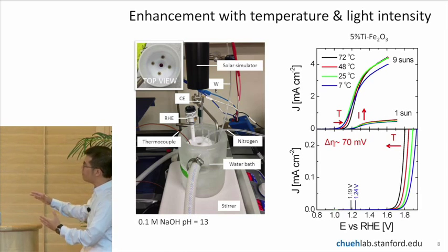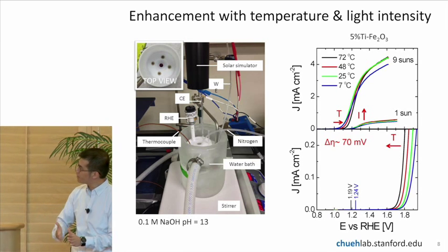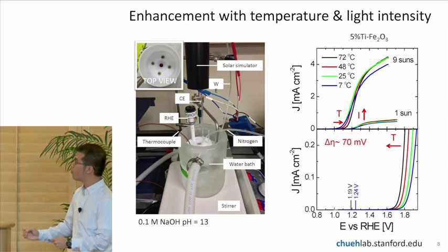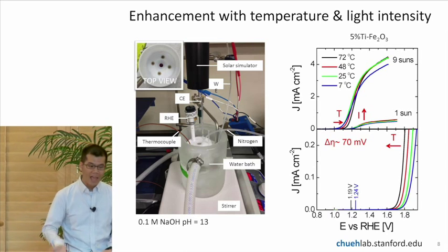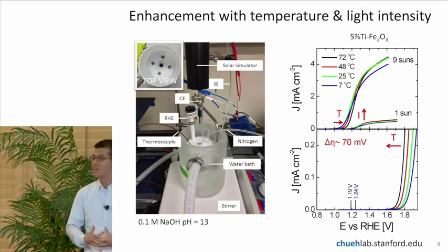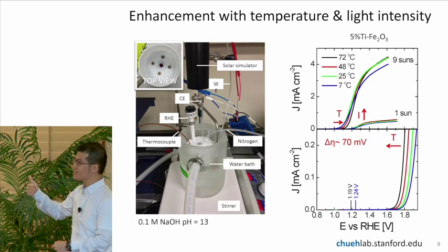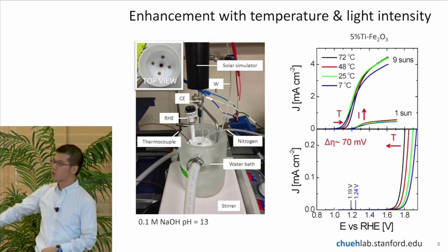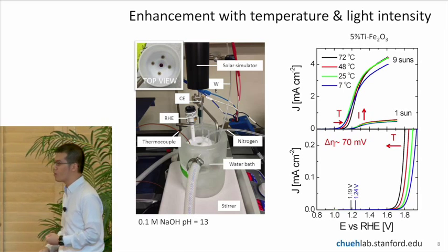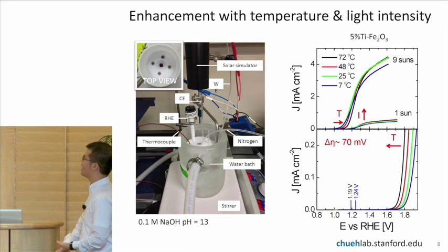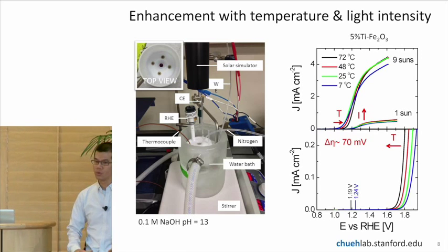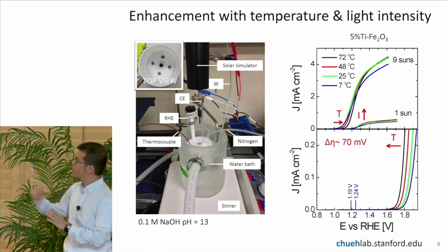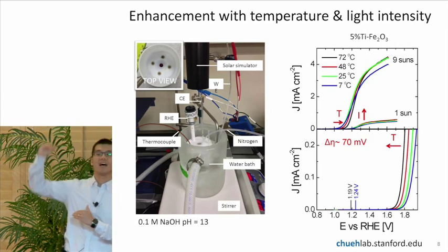And when we put the light in, it decreases a little bit. The shift is smaller than the gain you're getting, so that's good. And then furthermore, if we concentrate the light, we're able to substantially increase the current. And also by increasing the intensity of the light, you're also shifting the voltage to the left as well. So by carefully playing with temperature and light intensity, we're able to do what we want, which is push the voltage to a lower value on this plot and push the current higher.